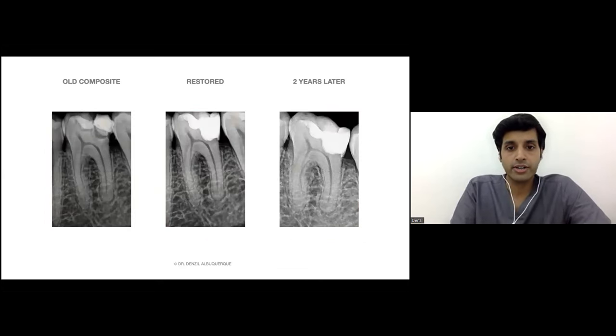And as we see the radiographs, we can see here, this was very close to the pulp, but it was not an exposure. We just went ahead with restorative principles and we can see there is again a good amount of dentine that is formed. That may be because of the angulations, but you could see the slight changes periapically have also healed. So there are absolutely no symptoms or even radiograph signs of deterioration.